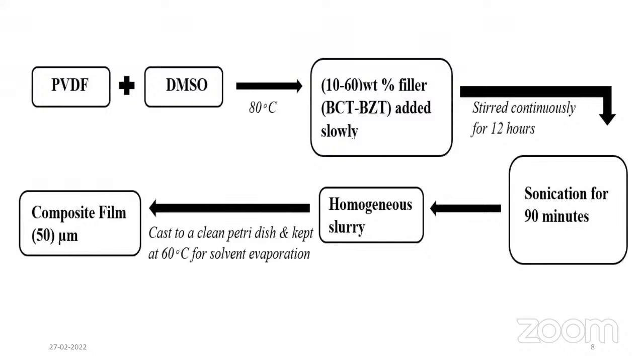Then the PVDF solution was prepared by using DMSO to dissolve PVDF, and at 80 degrees Celsius, when PVDF pellets were completely melted, nanofillers of BCT BZT were added in different amounts, 10% to 60%, and then stirred continuously for 12 hours. Then there was a process of sonication for mixing of filler and PVDF. A homogeneous slurry was prepared, which was cast into a clean petri dish and kept at 60 degrees Celsius for solvent evaporation. A composite film was formed with a thickness of approximately 50 micrometer.